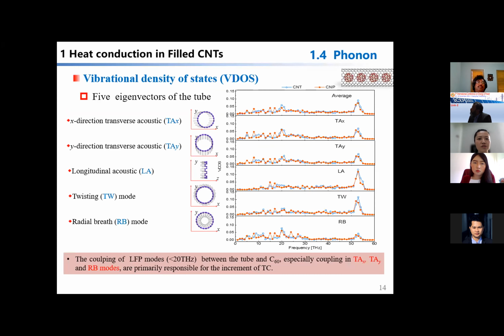I would like to give more details with VDOS, the vibrational density of states. We know that the carbon nanotube has five eigenvectors. With carbon-60 filling, since both the tube and the fillers are made of carbon atoms, there is small vibrational mismatch, that is, intrinsically high-level matching of VDOS between filler and tube. We can see that the coupling of LFP, low frequency phonon modes, less than 20 THz, between the tube and filler is especially coupling in XY direction transverse acoustic modes and radial breathing modes. We know that carbon tubes have radial breathing modes, just like a breath, which are primarily responsible for the increment of thermal conductivity.